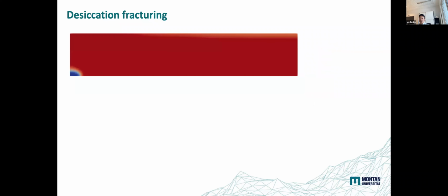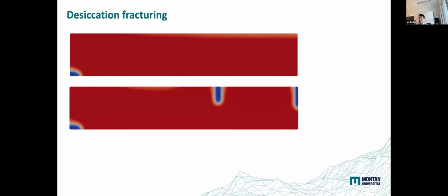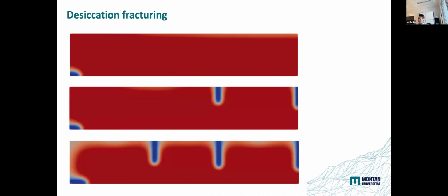So this is how the fracture developed. First, we saw some fracture development on this lower bottom corner, and then some vertical cracks started developing, and then we saw more vertical cracks, and at some point it reached some saturation point of the cracks, and then we did not see any new crack development. But all these nucleations of the fractures were picked up based on the energy minimization.